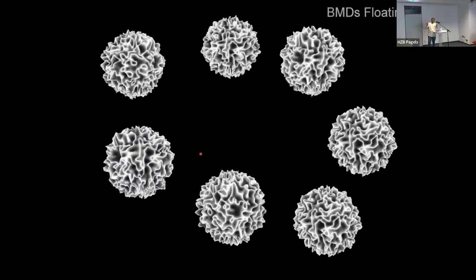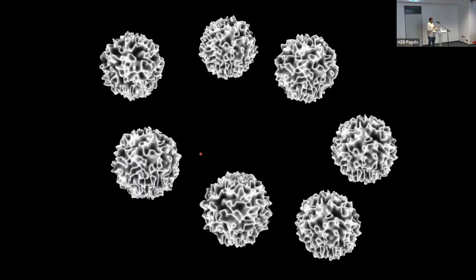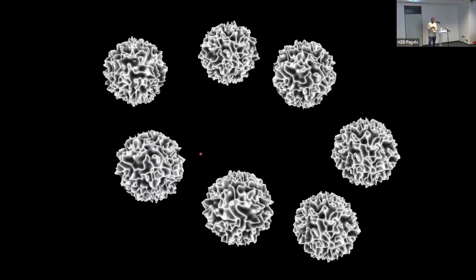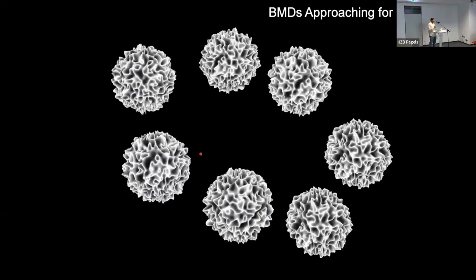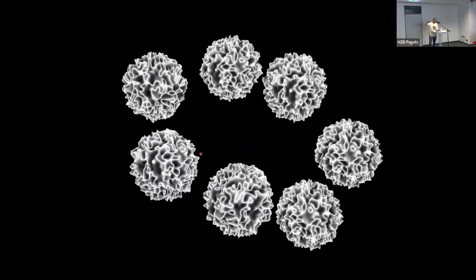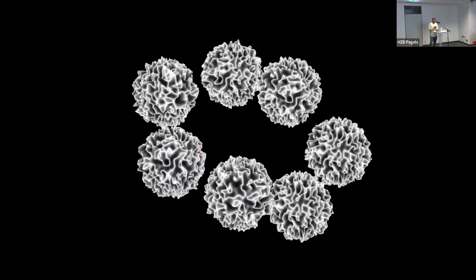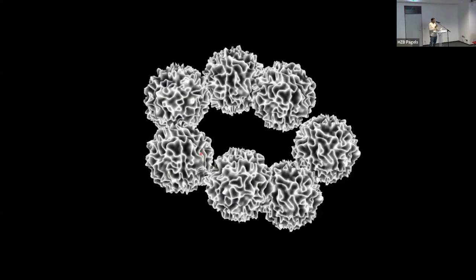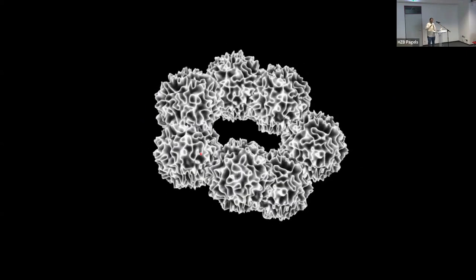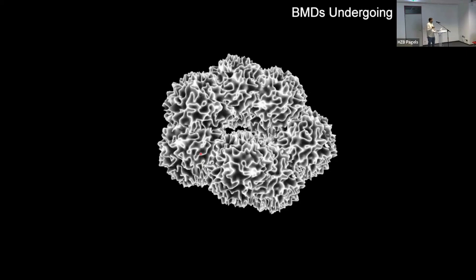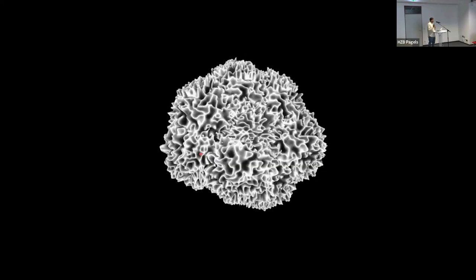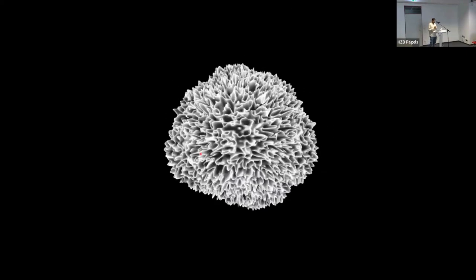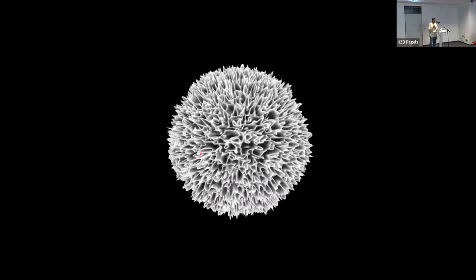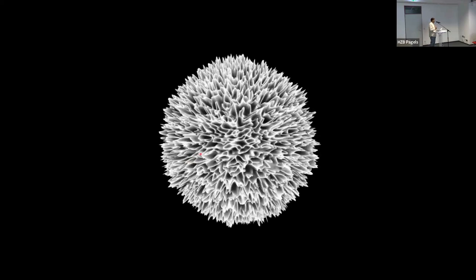So if you keep them away, you will get smaller nanoparticles, as small as 50 nanometers. But we also learned that by simply changing some reaction conditions, you can merge them together, right? Without changing their internal structure. That's why we use the word coalescence. That means they're merging, but the internal structure remains the same. And that allows you to get an even bigger DFNS particle, a bigger nanosilica particle, up to 1200 nanometers. Right? So that's the silica that we're using to design different heterogeneous catalysts.